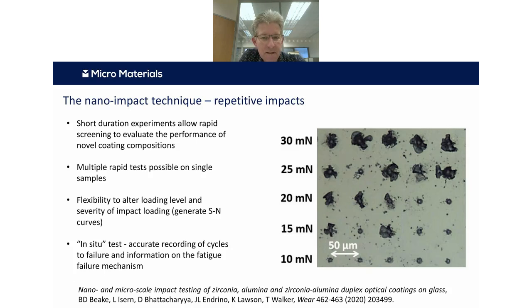So one of the nice things is it's done within our nanotest system, so it has all of the control that we can set for normal indentation and scratch tests, and we can set up these automated arrays or matrices of measurements. We can do multiple tests, set everything up together at different forces and different number of repeats at different positions. And that allows us to build up a statistical picture of the surface fatigue behavior of typically coating systems, and generate something like an SN curve, but from a single sample. So this is really a very useful test technique.